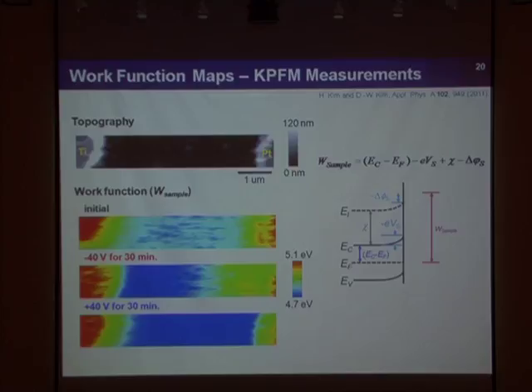However, the result is opposite—the work function under the platinum electrodes increased. And moreover, in all the bulk region, the work function is reduced. So we cannot explain that based on this carrier concentration contribution. We need another mechanism.